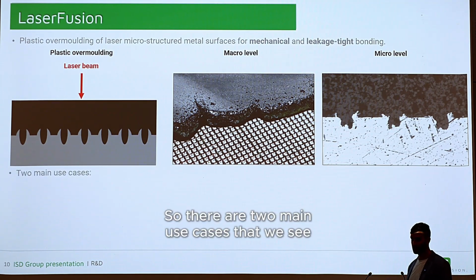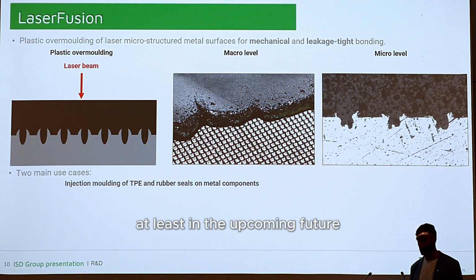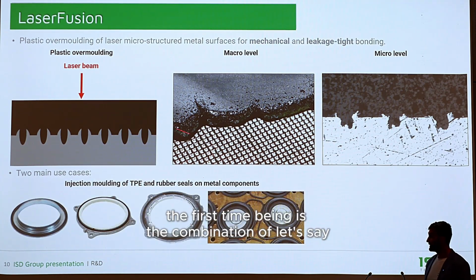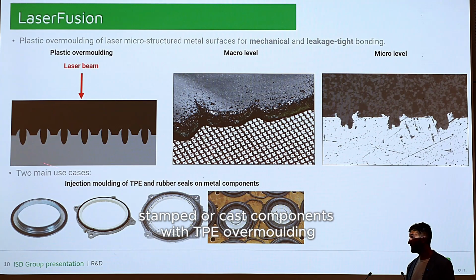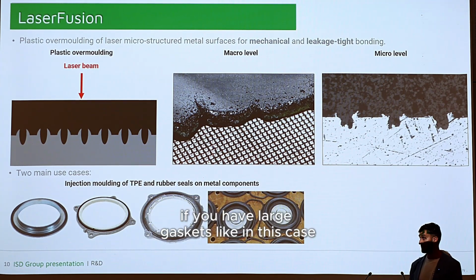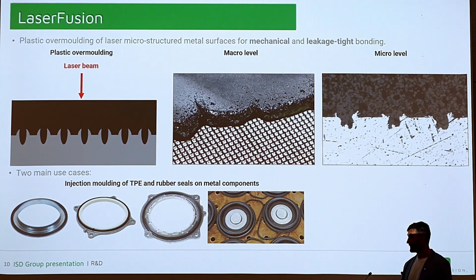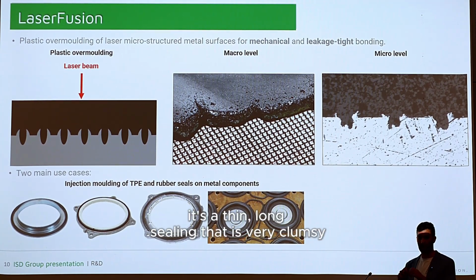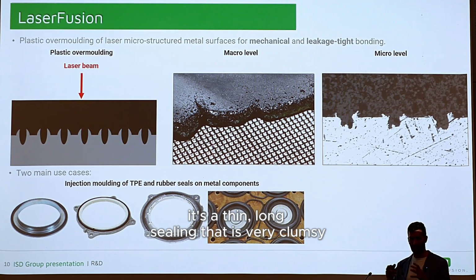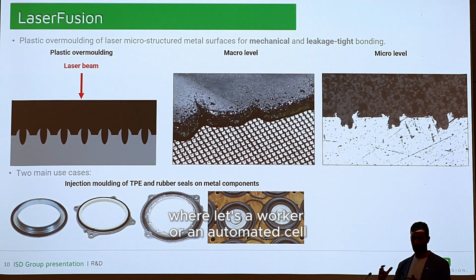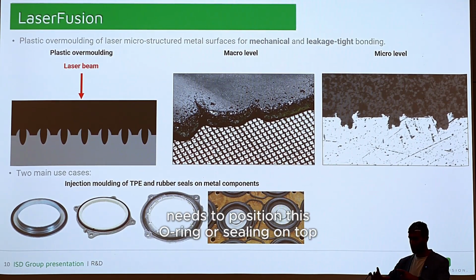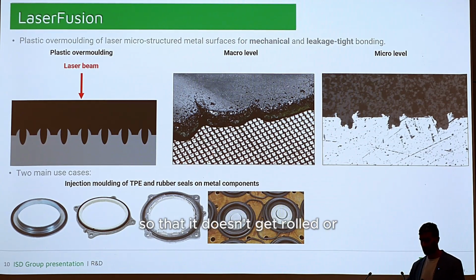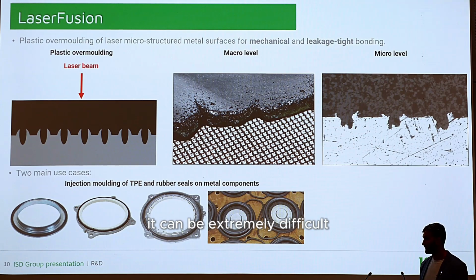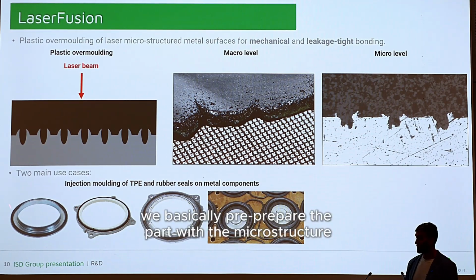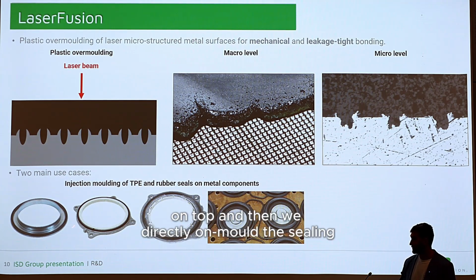There are two main use cases that we see, in the upcoming future and also in ongoing projects. The first is the combination of stamped or cast components with TPE overmolding. For example, if you have large gaskets like in this case, assembling this is extremely difficult. It's a thin, long sealing that is very clumsy. If you imagine this in serial production, where a worker or an automated cell needs to position this O-ring or sealing on top so that it doesn't get rolled or damaged during the process, it can be extremely difficult. But in this case, we pre-prepare the part with the microstructure on top, and then we directly overmold the sealing.